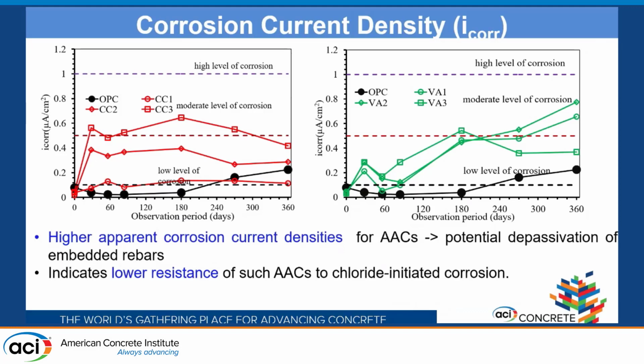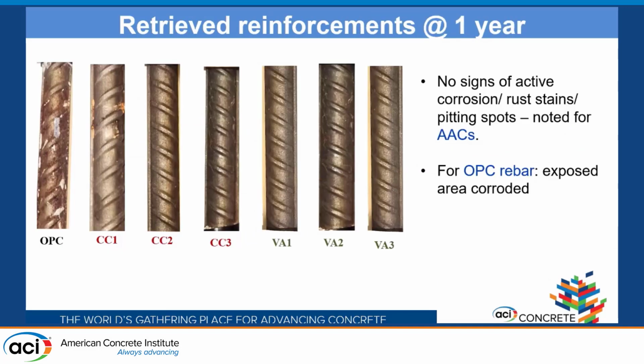So there's some onset of corrosion activity in OPC for sure, but let's check whether it is there or not. Coming on to the third, the corrosion current density results, we see higher apparent corrosion current densities for alkali-activated concretes, which show low to moderate level of corrosion in both CCs and VA based AACs. That indicates that there is some sort of potential depassivation of embedded rebars. These AAC systems are less immune to chloride-induced corrosion in particular. But to validate these test results, we had to retrieve the reinforcements at particular intervals. Here I am presenting the retrieved reinforcements at 1 year. You see all the extracted reinforcements from AACs had no signs of active corrosion, whereas the OPC rebar has corroded to a certain extent.